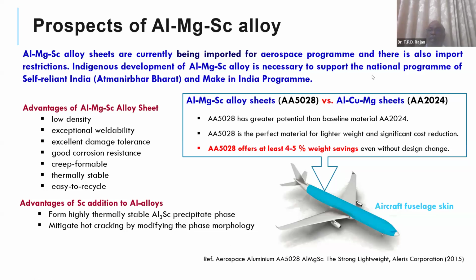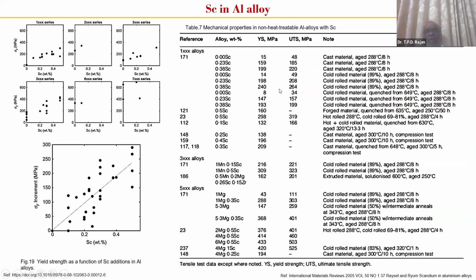Currently they use aluminum-copper-based alloys, which are highly dense, and are going for these aluminum-magnesium-scandium alloys, which are rare earth scandium-added alloys. The advantage is that it straight away reduces the density by almost 4 to 5%, and the strength is also increased. This aluminum-magnesium-scandium alloy, which is currently imported, is being indigenously developed, and we have transferred the technology of making the alloys into rolled sheets to an Indian industry, and the industrial trial is currently going on. And if you see the literature, we can see that a lot of studies on the impact of scandium on different aluminum alloys have been done.